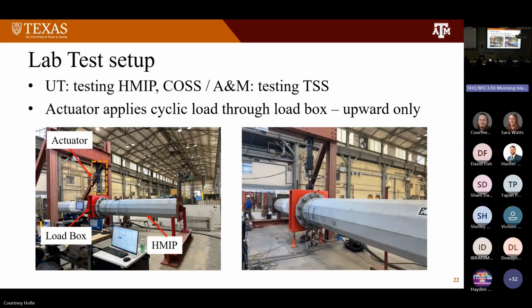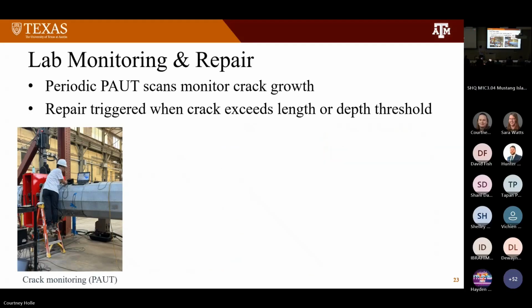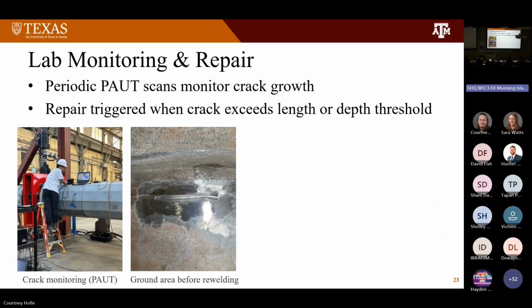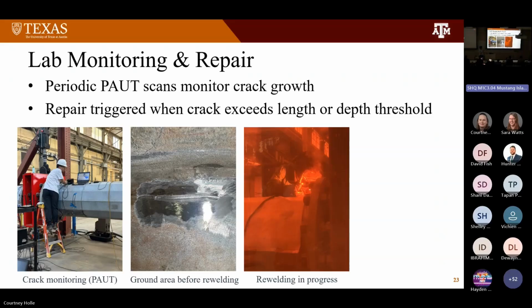So the fatigue cracks will occur over this point. Throughout the experimental test, we paused at designated intervals to inspect the test specimen using PAUT and measure the length and the depth of the crack. And if the crack exceeds a certain threshold, we repair it by grinding and rewelding.